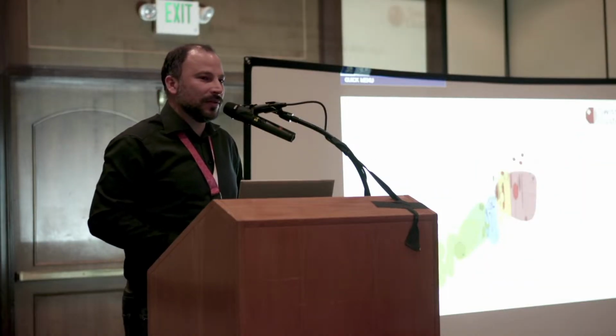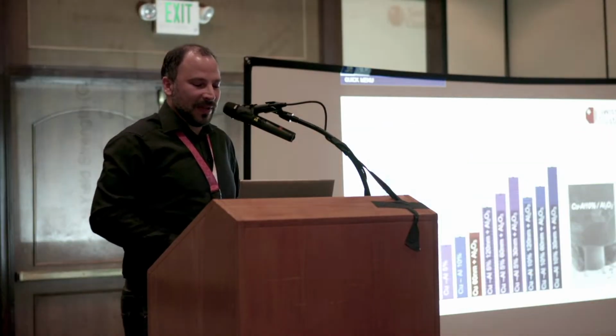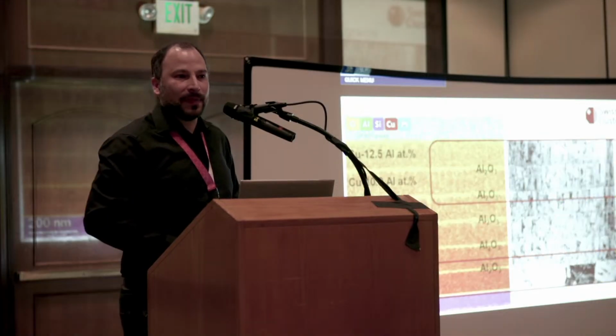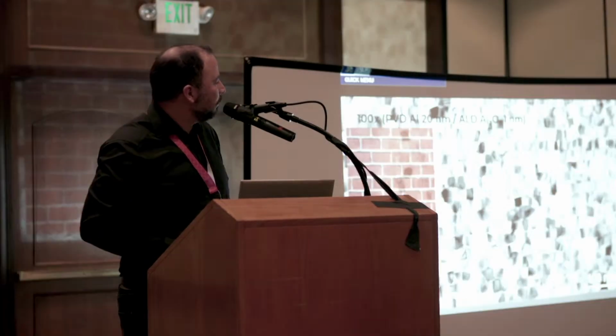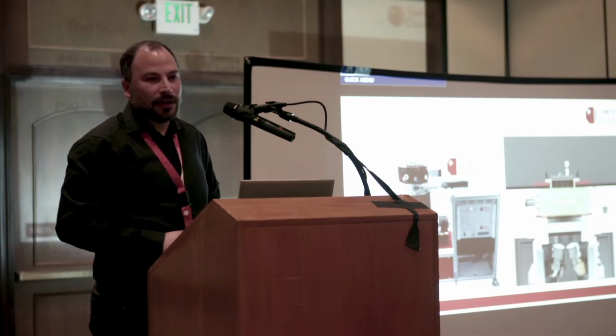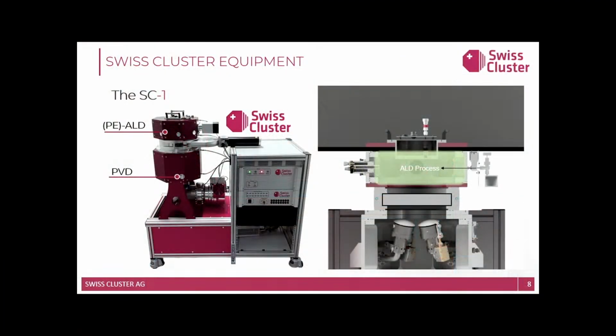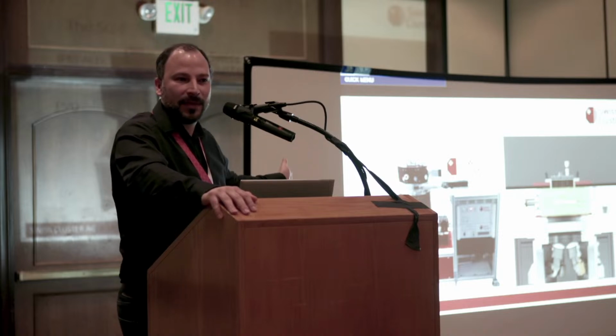Yes, that's a good question, and often a question that we get. So typically when we deposit ALD, you already down-react all of your gases, right? So it already deposits an aluminum oxide, which is a great barrier layer for preventing the desorption of water molecules. So you're already passivating your chamber. Once the ALD process is finished, you down-react all of the gases. There is, of course, a pressure difference between the two processes. The ALD has its own vacuum system working at a background pressure of 10^-3 millibar, right? And the PVD, we have it at 10^-7 millibar.